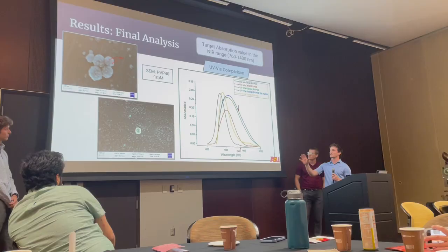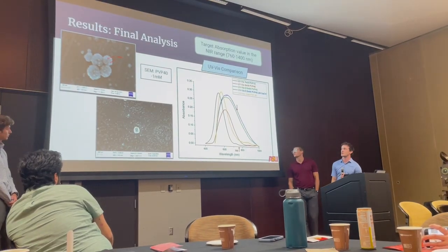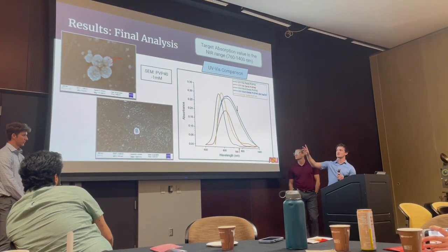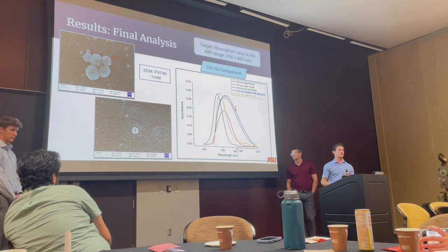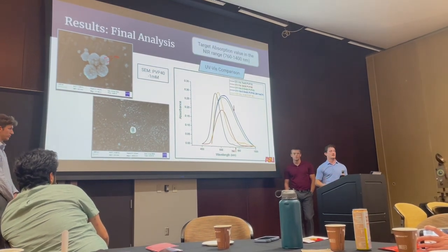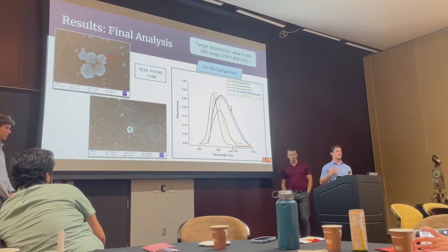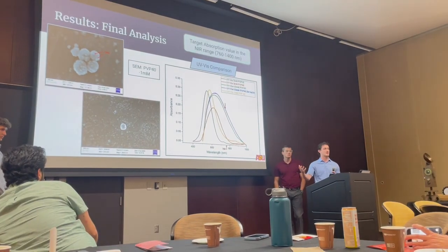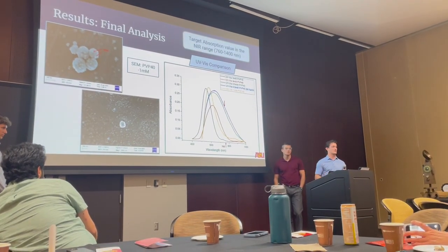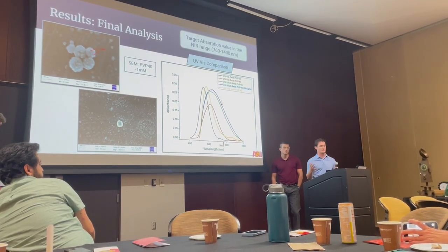Another great thing is that when we looked at the SEM of our smaller concentration particles, we started to see our branches forming very clearly, and we were getting longer branches. The reason that's important is that the peaks of these branches are what give us the absorbance at 760 and above, while the base of these peaks is what keeps it at a lower absorbance of about 540 to 600.